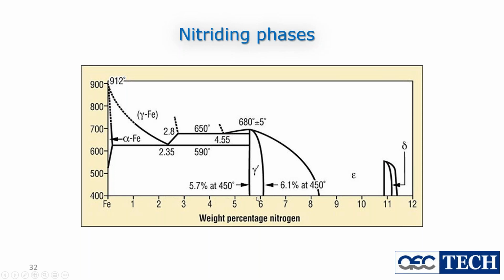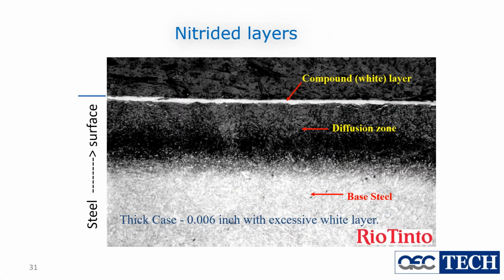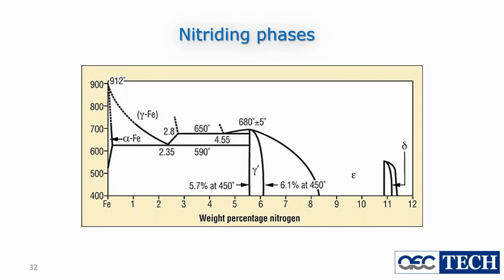We don't want it. If it's less than that, you're going to end up with the alpha iron or some compounds with less nitrogen in it, or gamma iron, which has less nitrogen in it, is less hard. So we don't want that. So the gamma prime is the one we want. So yeah, it's just like extrusion. It's time and temperature, right? Yes, exactly. And then this temperature, it should be right at the right range, and also the concentration of the ammonia in the mixture to make the right phase gamma prime.